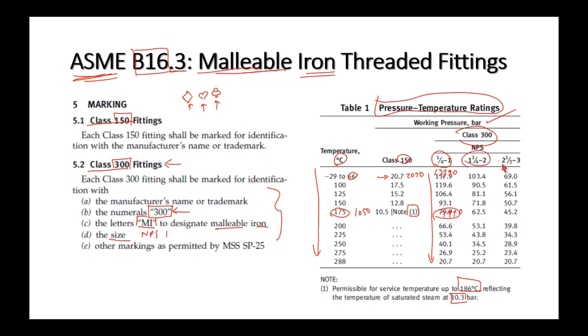Then the other thing is, as our fittings become larger in diameter, we know that the stress in the vessel, in the cylindrical component, varies with diameter of the vessel. And so the larger the diameter of the vessel, the thicker a boiler shell has to be. Well, how do we deal with this with fittings? We don't make them thicker. What we do is we reduce the allowable pressure rating as the diameter increases. So for 1 1/4 to 2 inch, it's only good for 10,340 kPa, and for 2.5 to 3 inch, that malleable iron fitting is only good for 6,900 kPa. So just so you're aware, as fittings increase in diameter, they're rated for lower pressure, and as their temperature increases, their pressure rating also decreases.